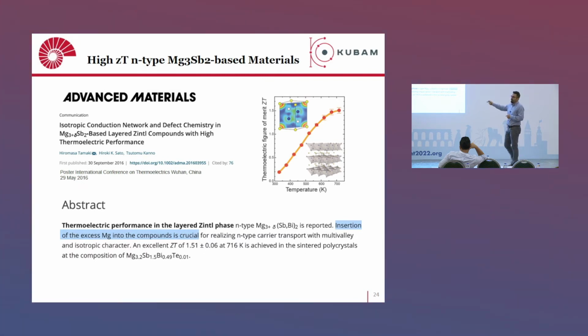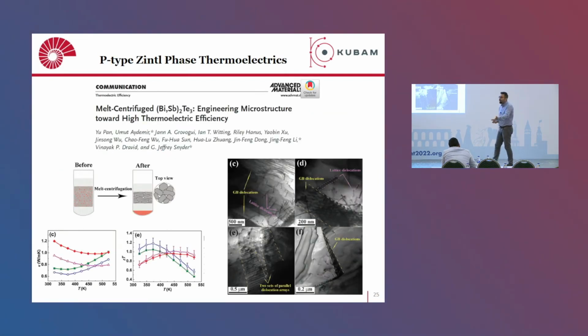To make this n-type, there is a unique strategy. You have to add excess magnesium. When you start making this material, you have to add some excess magnesium to suppress the formation of this magnesium defect, which leads to this p-type character. So we knew that you can make this material n-type. But then we thought, how can we improve the thermoelectric efficiency, or what else can we do? So we applied a melt centrifugation method to this material.